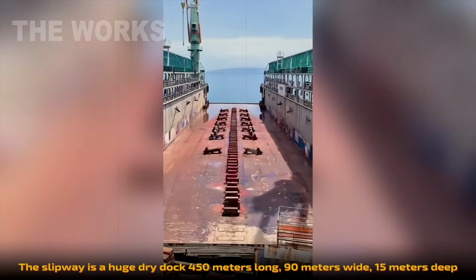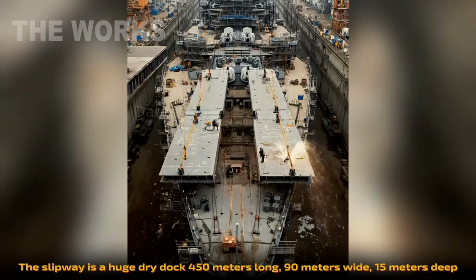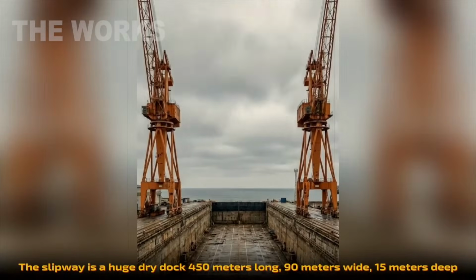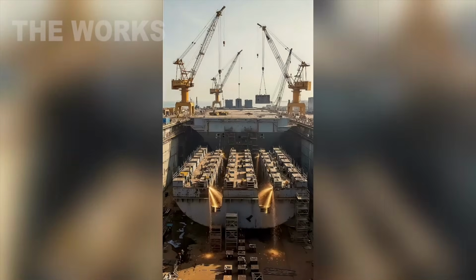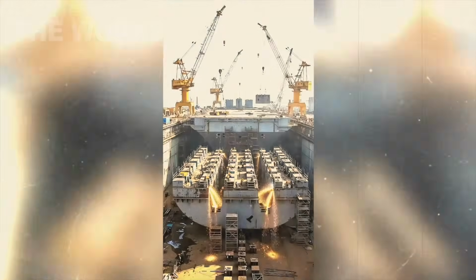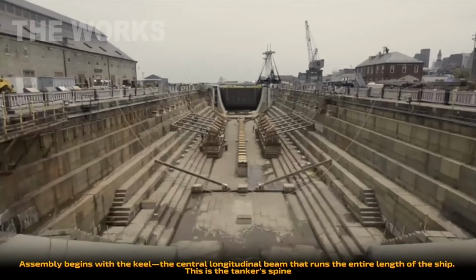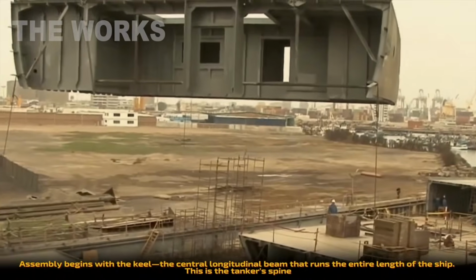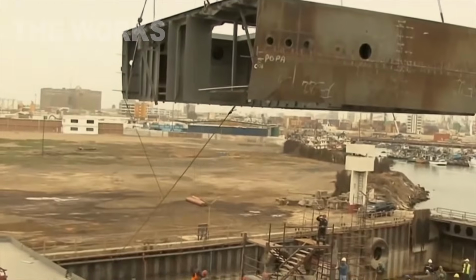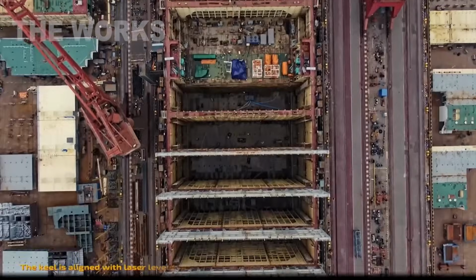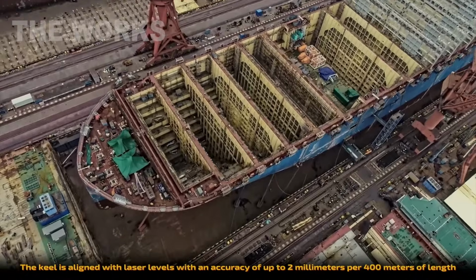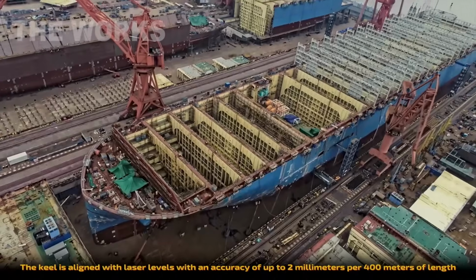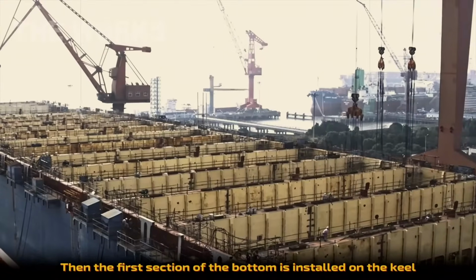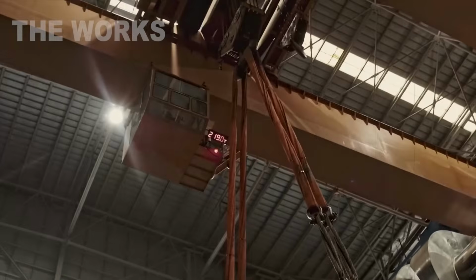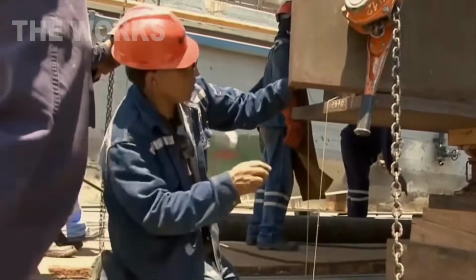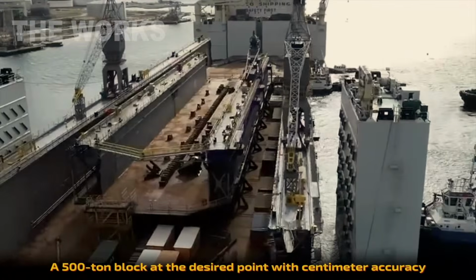The slipway is a massive dry dock, 1,476 feet long, 295 feet wide, 49 feet deep. This is where the entire hull comes together. Assembly starts with the keel, the central longitudinal beam running the full length of the ship. It's the tanker's backbone. Everything depends on how precisely it's positioned. The keel is aligned using laser levels with accuracy down to 0.08 inches over 1,312 feet.